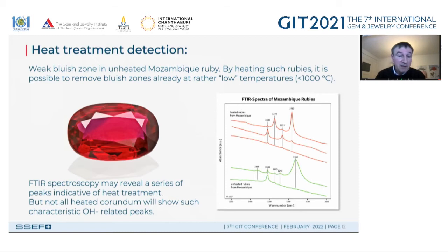What you see in the picture is a ruby of very exceptional quality. And what you see in the corner is a bluish zone. This Mozambique ruby, such material has been and is still heated at low temperatures in oxidizing conditions to finally get rid of this blue zone. When you look at the stone, you will not see this blue zone as you see it here in this transmission picture.